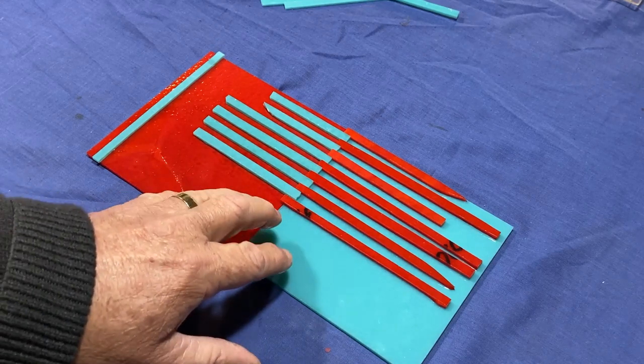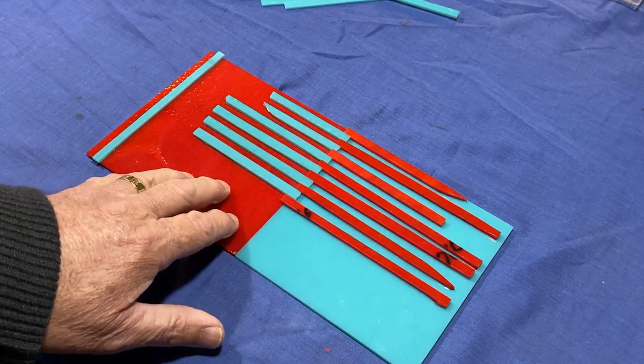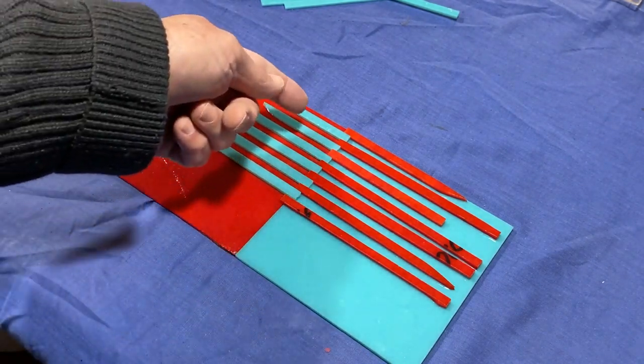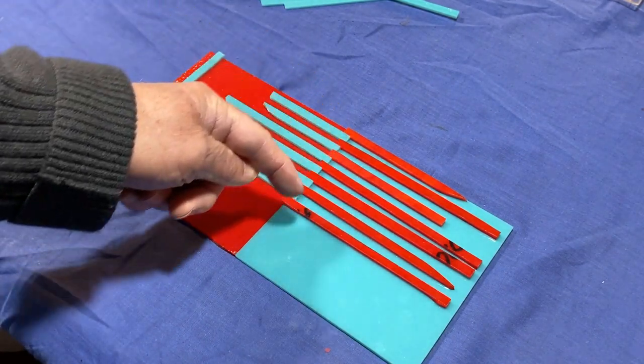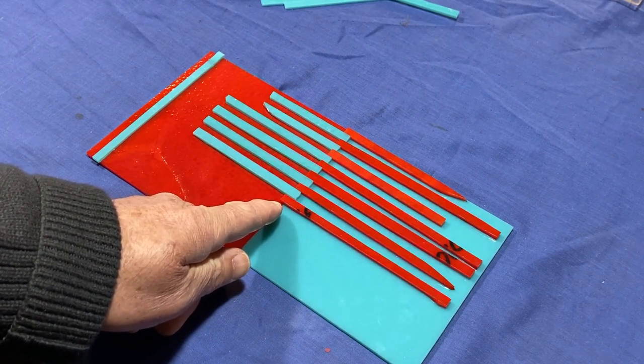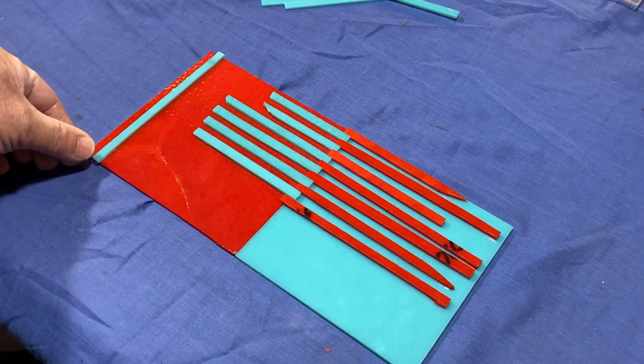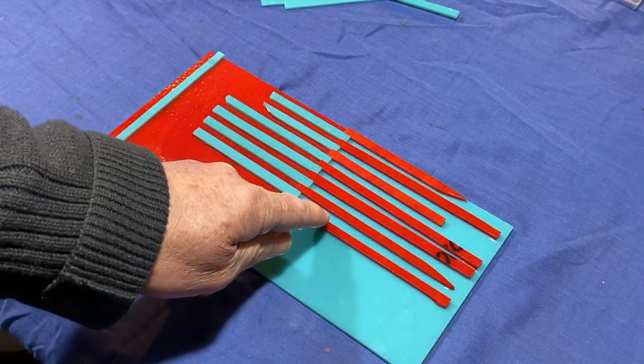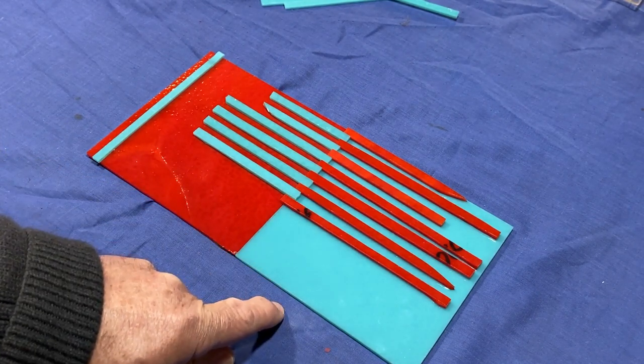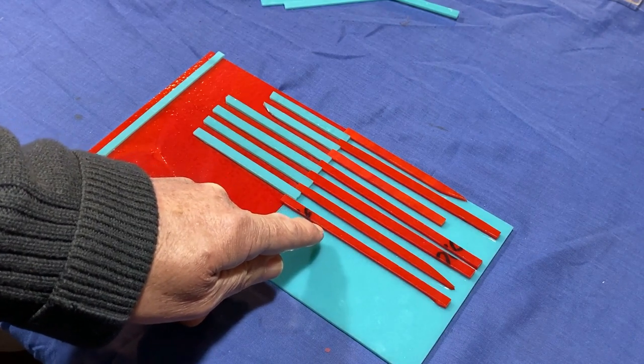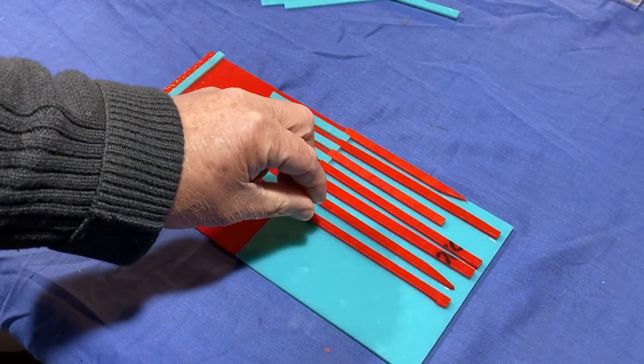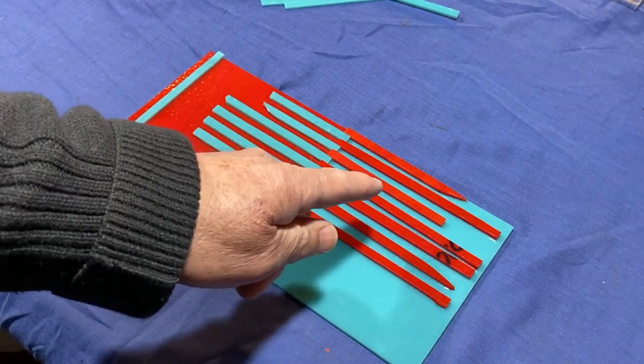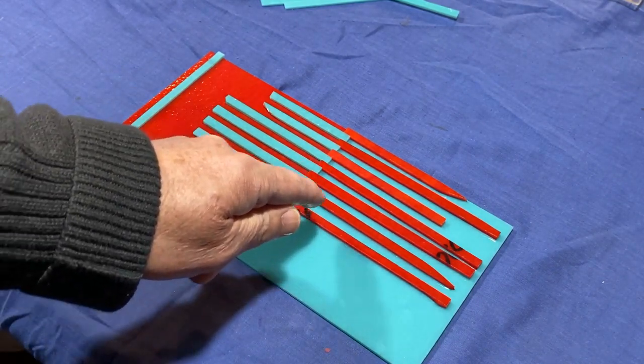I've got all the glass cut and this is basically what I'm going to do. I've got the tomato red one side, turquoise on the other and then I'm going to have tomato red strips on this side, turquoise strips on that side and I'm going to stagger the lengths of these right across that join so each strip will go over that join just a couple of mils. Then on the ends I'm going to have a single strip of turquoise here and a single strip of tomato red there. Now remember this is three mil strips on three mil on another three mil so the thickness around here is about nine mil. Now I am going to do a full fuse to flatten this out completely, which means these things are going to move a bit as it pushes the glass around. So while it's a geometric pattern in the end I can guarantee it's not going to look like nice straight edges, but that's fine because we're also going to get the reaction between all of these as well.